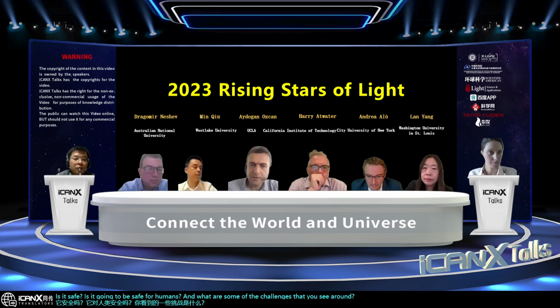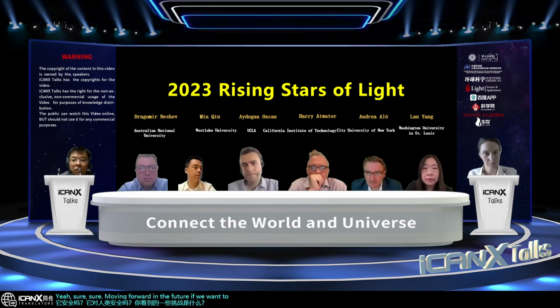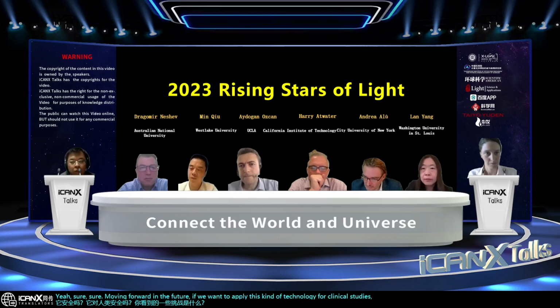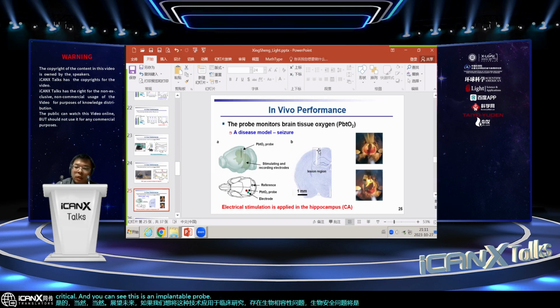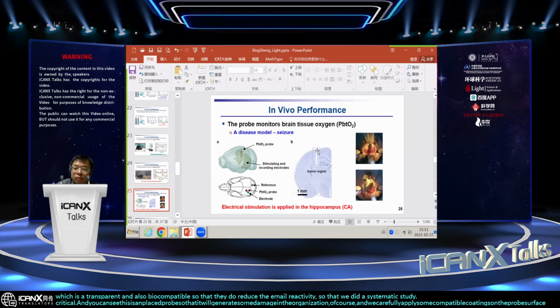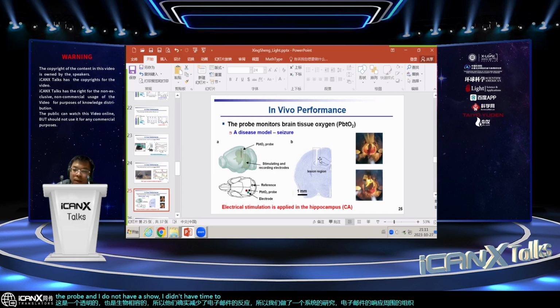Yeah, sure. Moving forward, if we want to apply this kind of technology for clinical studies, the biocompatibility and biosafety issues will be critical. This is an implantable probe, so it will generate some damage in the tissue, of course. We carefully apply biocompatible coatings on the probe surface, which is transparent and biocompatible, so that it will reduce the immune reactivity. We did a systematic study of the immune response of the tissue surrounding the probe. I didn't have time to show all the details here. We compared it with conventional probes, for example commercial implants and optical fiber-based implants, and they show a similar reaction response.